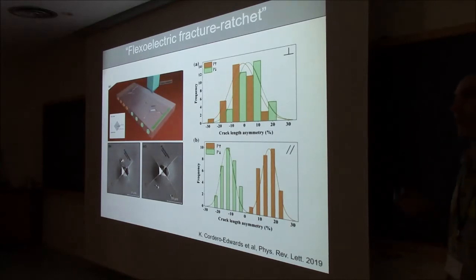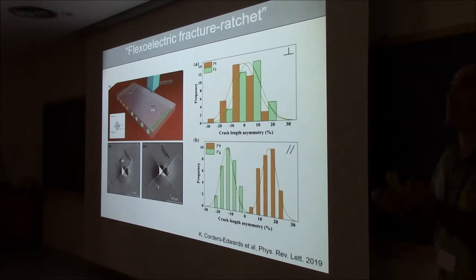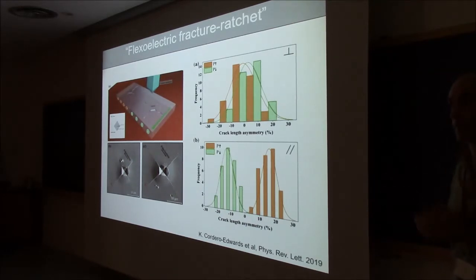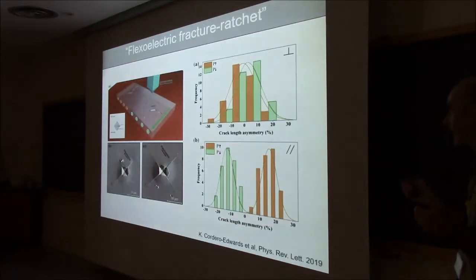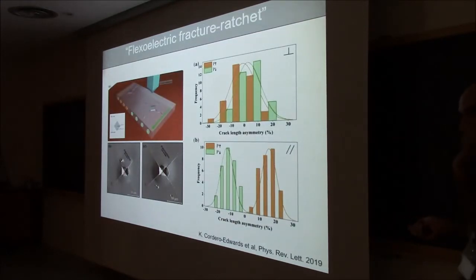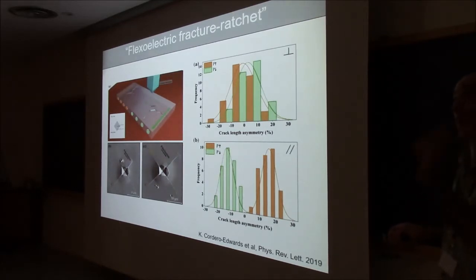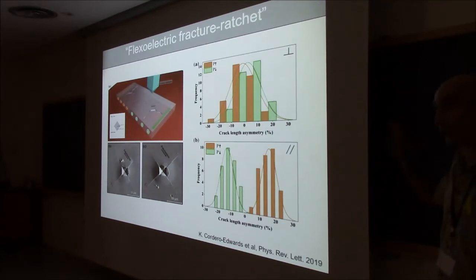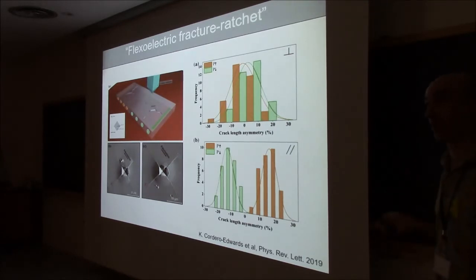So if you have an actuator that is fatiguing due to built-in stresses that are fracturing the material, we think that playing with the polarity of the actuator might mitigate the fatigue of the material. Okay. Let me emphasize, this is really profound, and it only is possible if you have the combination of flexoelectricity and piezoelectricity. If you had either effect alone, you would not see such asymmetry.